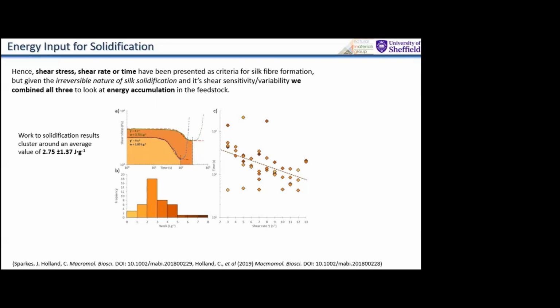Now, we can take silk out of the animal and we can cook it, we can fry it, literally in little pans, DSC pans, actually, and work out the energetic cost of cooking a silk. And when we start to compare this to our DSC work, we find out that the denaturation entropy, the energy work required to spin a silk by heating it up, is about 1.78 joules per gram. So from a biologist's perspective, this is the same order of magnitude. So I'm a very happy chap. This is actually incredibly close to one another because it highlights that our ability to look at the flow-based efficiency of silk solidification is very, very similar to the brute force way of getting silk to solidify just by heating it up. So these tools and techniques are relevant.